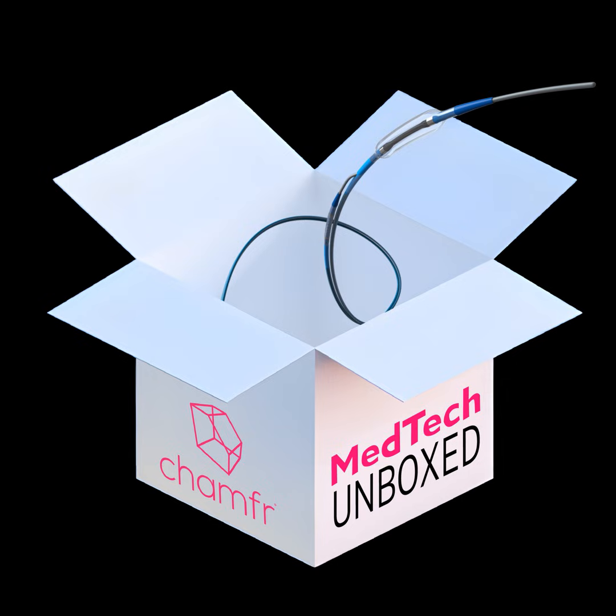We also use those a lot in stent deployment, right, where that PEBAX layer is going to provide additional friction. It's going to be a little bit softer against the tissue, softer against the stent, but still maintain the rigidity and control diameter that a nylon balloon offers. And then the puncture resistance of a multi-layer balloon is also far higher than a single layer balloon. So there are a lot of reasons that we do that. This may be a small part of it.